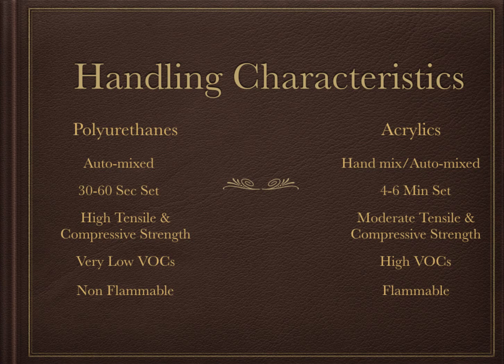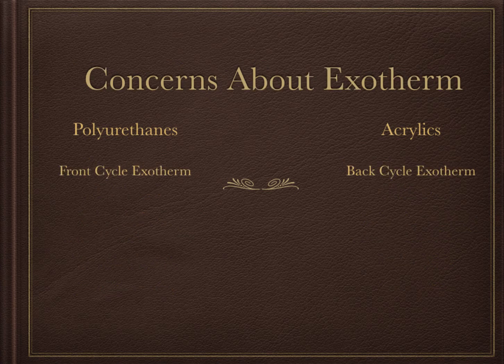Okay. So the heat cycles, both of these materials generate heat, and they call that exotherm. That means it gives off heat. And so when both these materials are mixed, the process of exotherm is what actually allows them to polymerize and set to the desired consistency that it was designed for. So the key difference here is there's two different kinds of exotherm. Polyurethanes have what's called a front cycle exotherm, and what that means is that as soon as the material is mixed, it gets hot immediately. There's a heat spike, and then the heat begins to dissipate around 4 minutes. It starts to dissipate pretty rapidly.